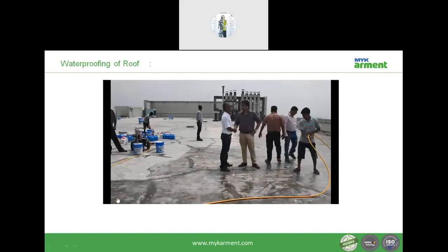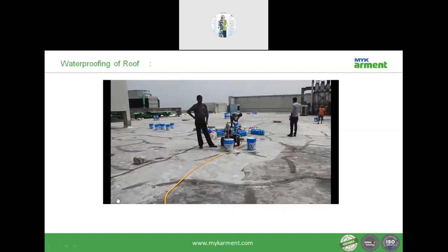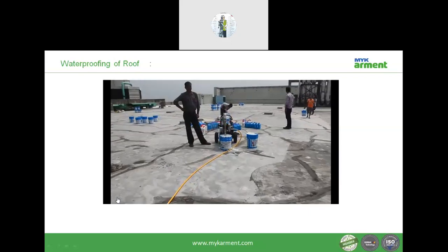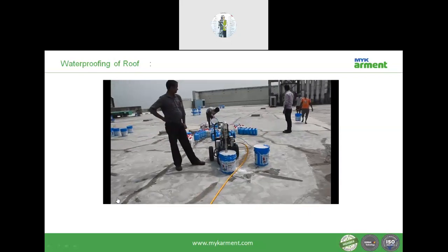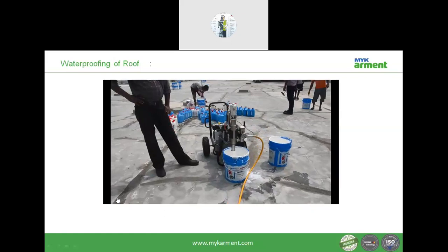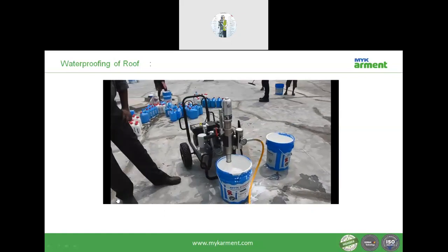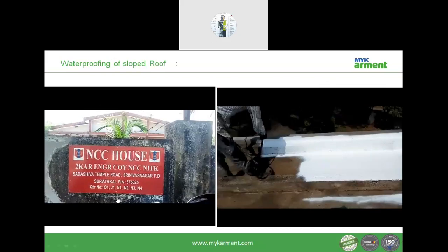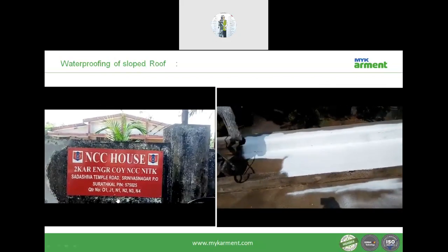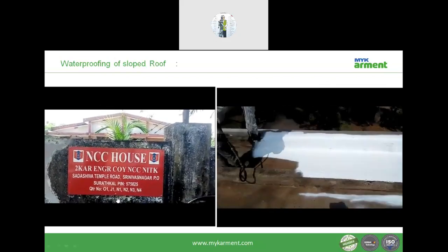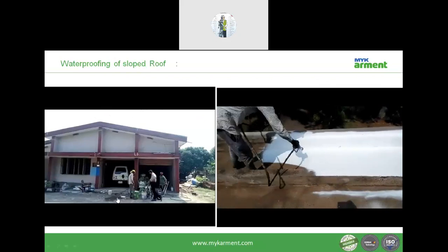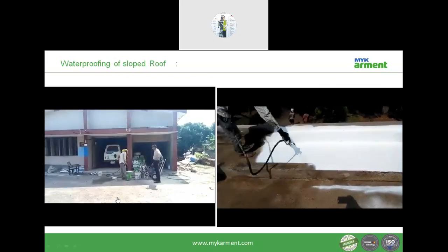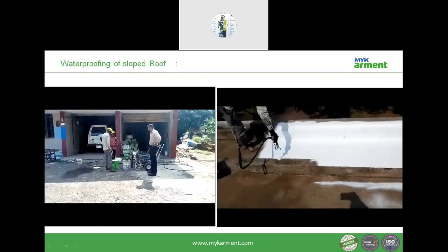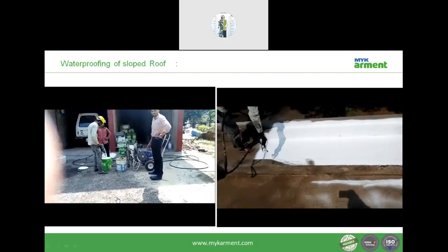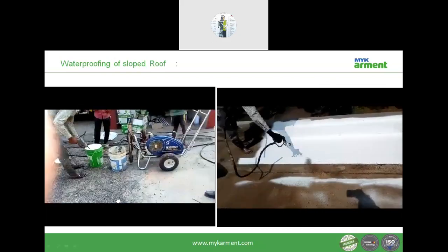This is one of the projects where you can see there are cracks on the screed. The screed cracks have been treated, and then it is applied with a polyurethane based coating system using a spray applied pump. And this is for an inclined roof slab, where the polyurethane coatings are applied on the inclined roof of a 30 years old building, an NCC house, where the polyurethane based coating systems have been applied for the protection of the concrete structure.